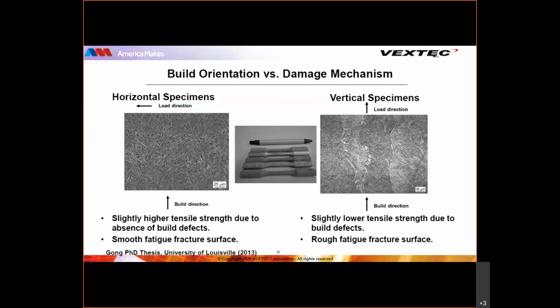And on the right-hand side, the build direction and the loading direction are parallel and collinear. Based on experimental data, it has been observed that when the build direction and the loading direction are perpendicular, this material exhibited higher tensile strength and a smoother fracture surface, as opposed to the other case where they were collinear or parallel. It had a slightly lower tensile strength. There were build defects that became active, and it had a rough fatigue fracture surface. Again, empirically and through observation, we understand that.